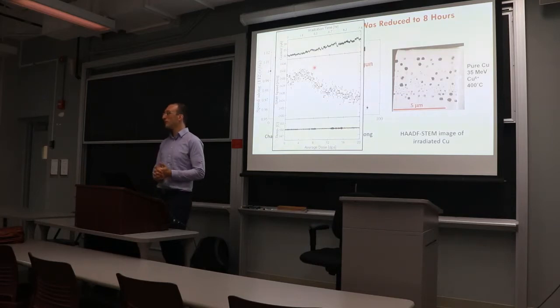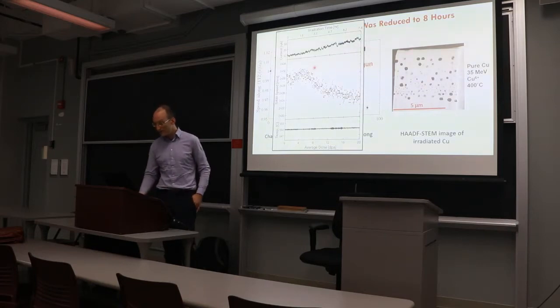You've done this before. I don't know if anyone's ever made a TEM specimen the old way, grinding down to a 300 micron disc, polishing on a lapping fixture, twin jet polishing until the laser pokes through. I did one. That was enough to motivate me to think about other ways to do it. So I've done it once.